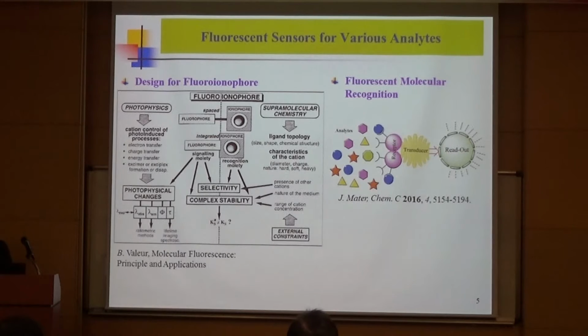Traditionally, the fluorescent molecular sensor works in dilute solution, and it is difficult to separate and recycle the sensor for multiple use. Application of sensor devices based on the morphology of thin film or membrane morphology may overcome this problem. However, the limited solid-liquid interface and poor mass transfer may cause low sensitivity. Therefore, we try to propose the fabrication of fluorescent sensing nanofibers based on electrospinning technique to gain much higher specific surface area as novel sensing devices.